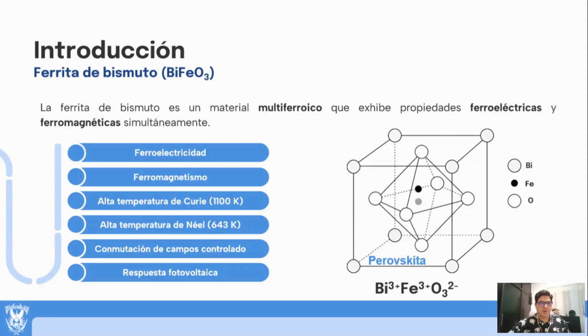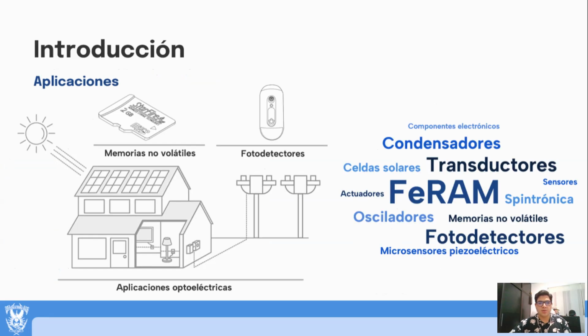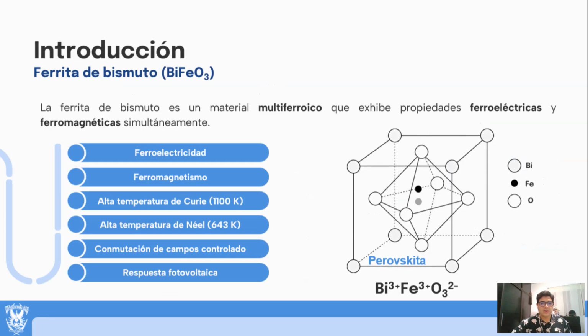Lanthanum-doped bismuth ferrite thin films have emerged as promising multiferroic materials due to their unique coexistence of ferroelectric and magnetic properties at room temperature, making them attractive for applications in data storage devices, sensors, and renewable energy systems. Pure BFO crystallizes in a distorted perovskite structure, R3C space group, and exhibits a high Curie temperature, 830 degrees Celsius, for ferroelectric order and Néel temperature, 370 degrees Celsius, for antiferromagnetic order.